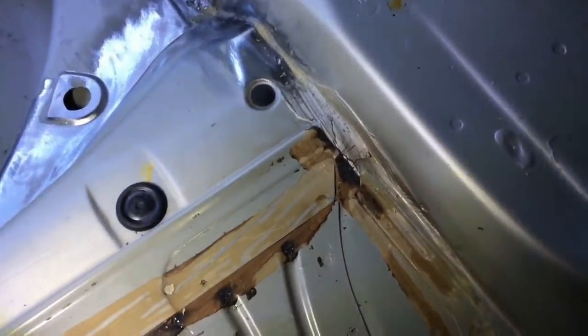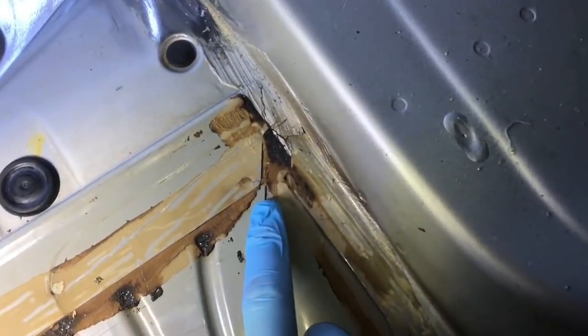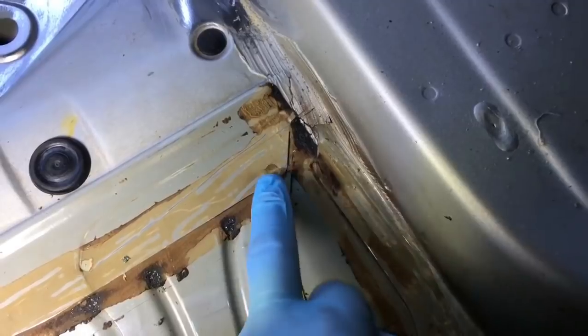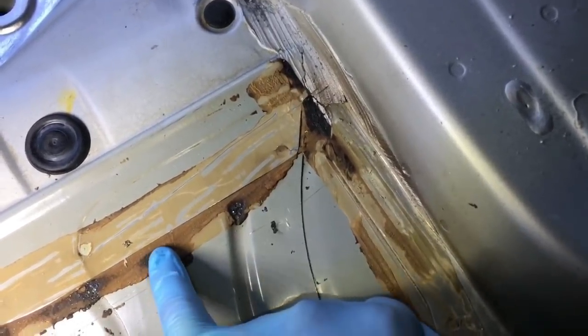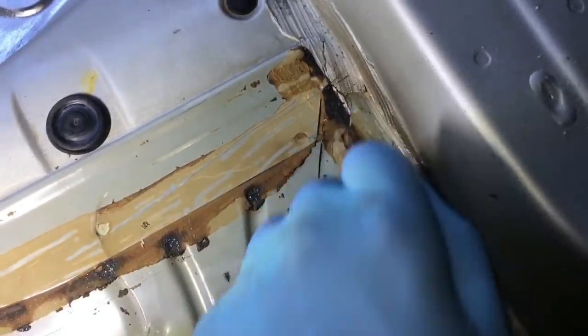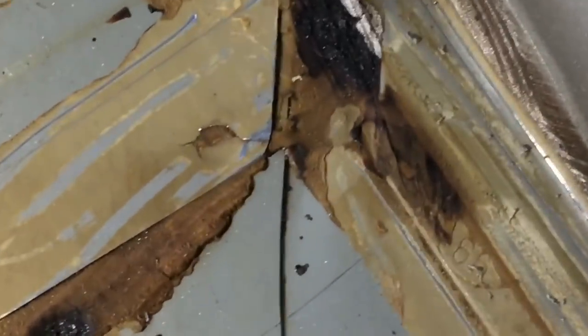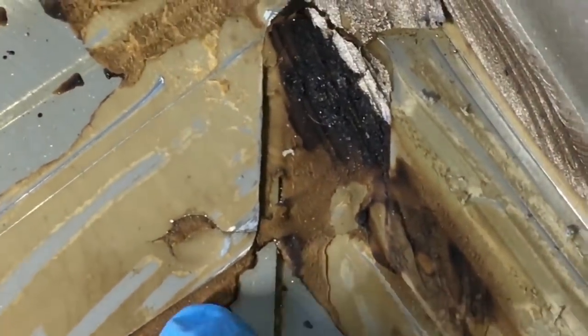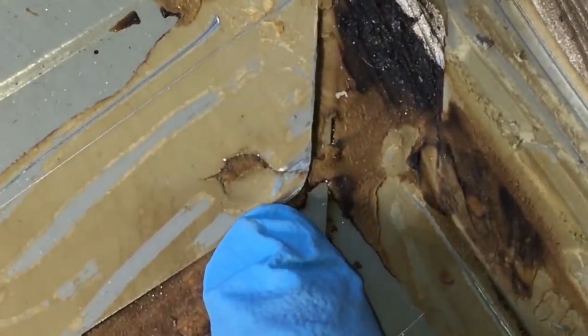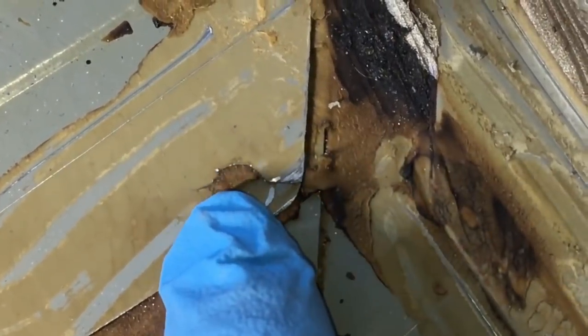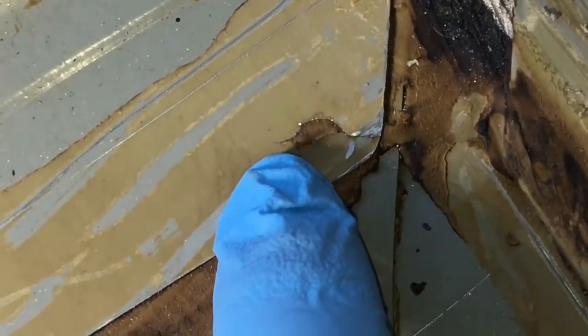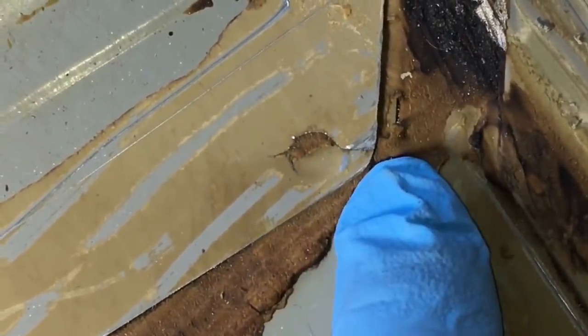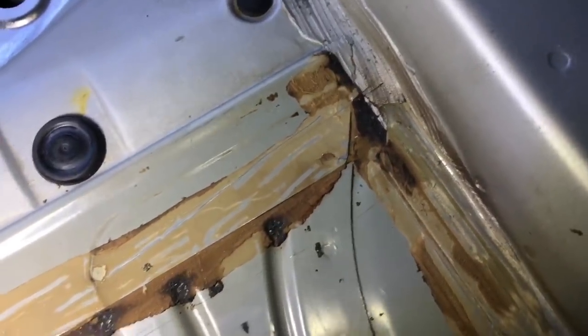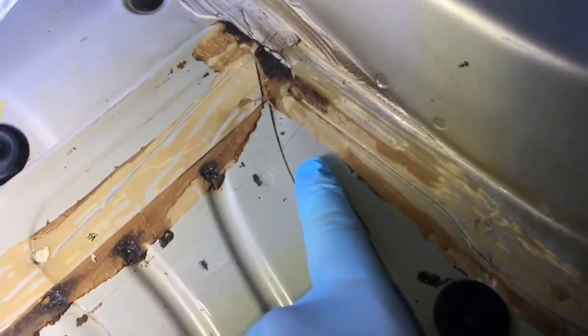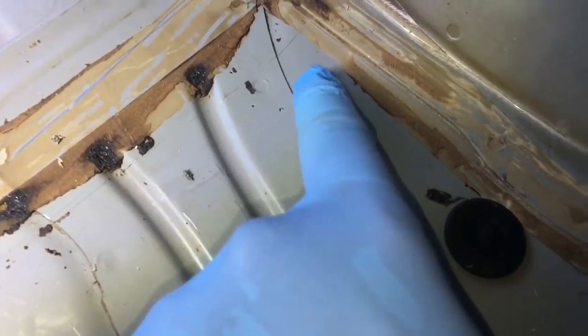And interestingly, we've got a broken spot weld. I haven't yet levered anything with a screwdriver. I haven't touched or drilled out any of these in any fashion. You can still see it's sealed here where this seam sealer was used with a scraper that way. So we haven't touched this panel. And there's one spot weld, really hard to see, but the circular spot weld is in front of my blue glove, and it's got a crack going out to the edge of the panel that way, and also a crack going in towards the panel this way, probably only about 3mm that way and about 4mm that way, because the spot weld is 6mm wide. But it gives you an idea of the flex that we're slightly seeing, and a very, very slight drop. It's so small it's not really worth mentioning, but we're here so we'll video it.